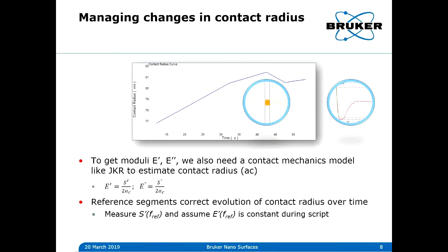I mean, the contact area is definitely a factor. You have to preload, right? And if you want to get some signal, you need enough amplitude to do a measurement. That means your preload needs to be a bit larger than that amplitude. So you need to have the tip have a fair amount of load on it that causes some deformation. And so it's not just the tip radius is what I'm trying to get at. It is a combination of the preload and the tip radius that gives you a contact radius. And that will be kind of the starting point to the resolution. Of course, you have a strain field under the tip that's often bigger than the contact radius.